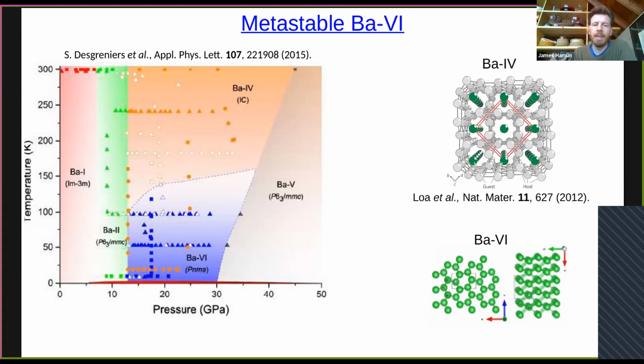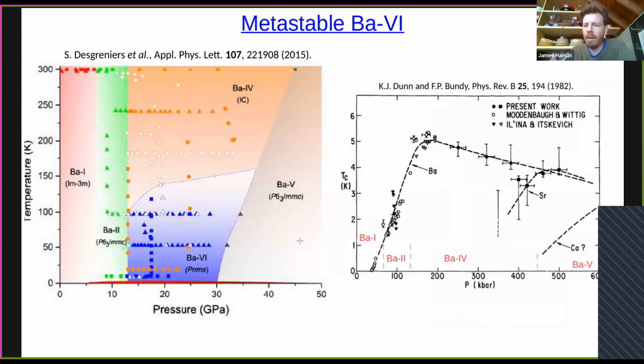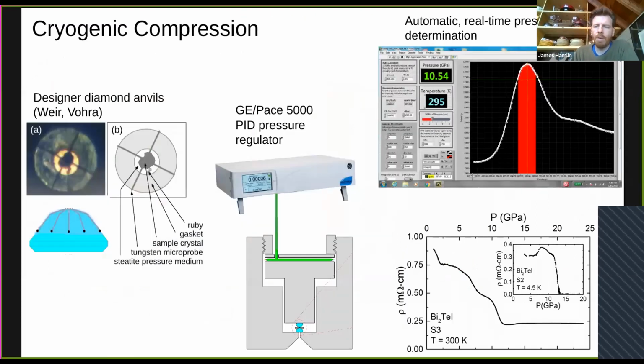And so we wanted to see if perhaps this barium 6 phase would have a different superconducting behavior than barium-4. This was the previous work on superconductivity in barium. So basically it becomes superconducting in barium-1 and gradually rises. And then within the barium-4 phase, Tc kind of gradually decreases. So that was the previous work. And whoops, I'm going backwards. So what did we find?